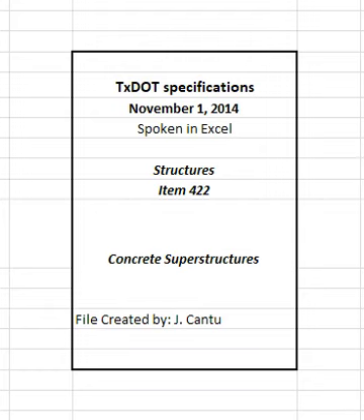Water may be added to the concrete before discharging any concrete from the truck to adjust for low slump provided the maximum mix design water-cement ratio is not exceeded. Mix concrete after introduction of any additional water or chemical admixtures in accordance with Section 421.4.6, Mixing and Delivering Concrete. Do not add water or chemical admixtures after any concrete has been discharged.